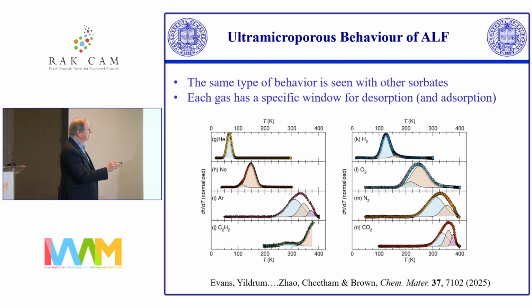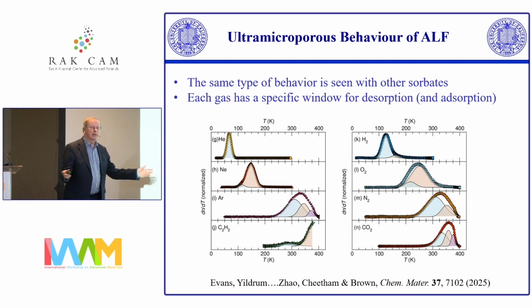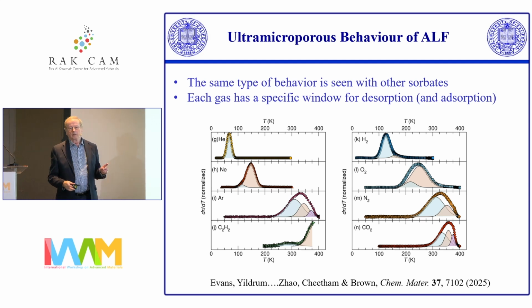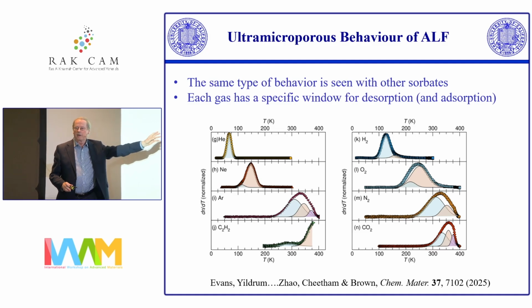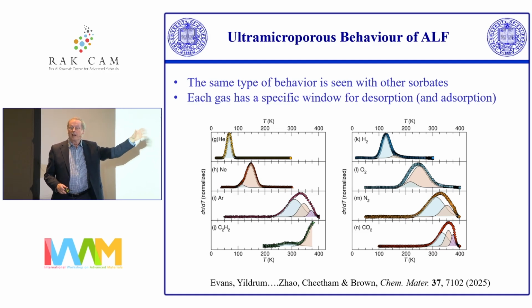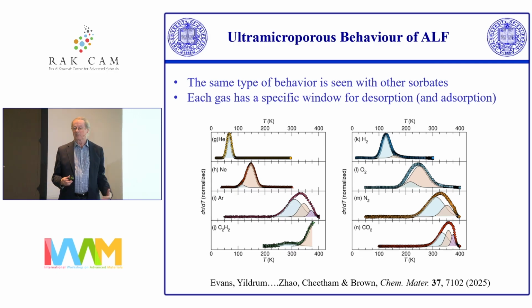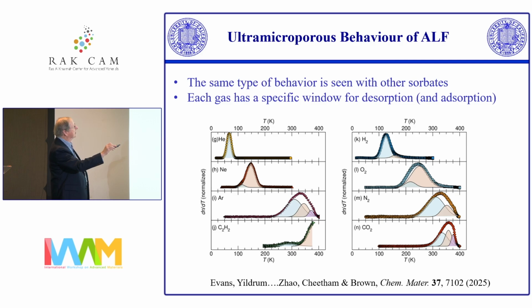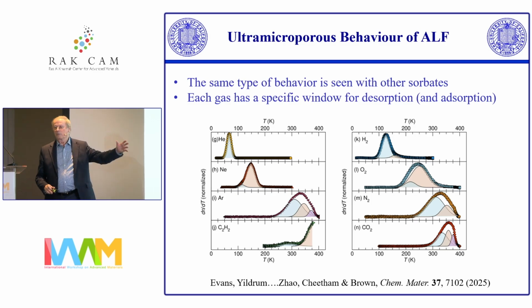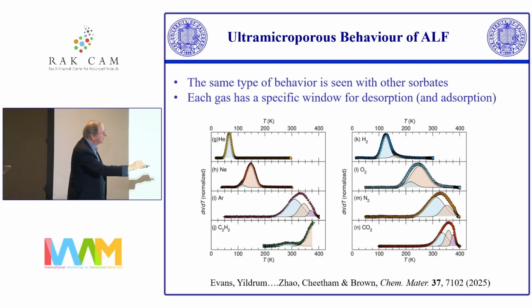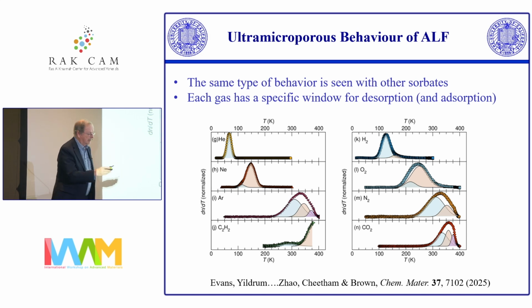And we have that data not only for inert gases, we have it for acetylene. See, acetylene, we kind of never get to the gating temperature. There's some hypothetical gating temperature at very high temperatures, but at that temperature, the thermodynamic adsorption has disappeared, so nothing goes in. And this is the gating temperature for hydrogen here, for oxygen, close to room temperature. Nitrogen, again, is very high. That's why nitrogen won't go in. And CO2 is very high as well, but it has a very good heat of adsorption.